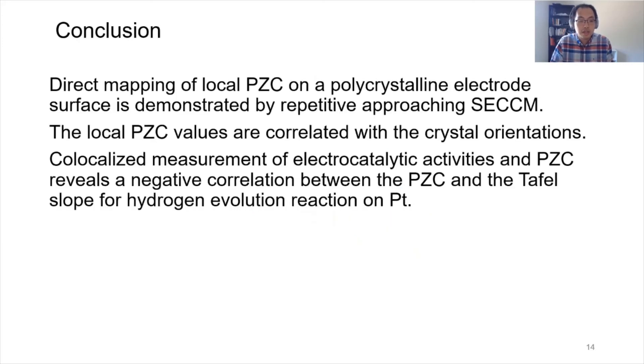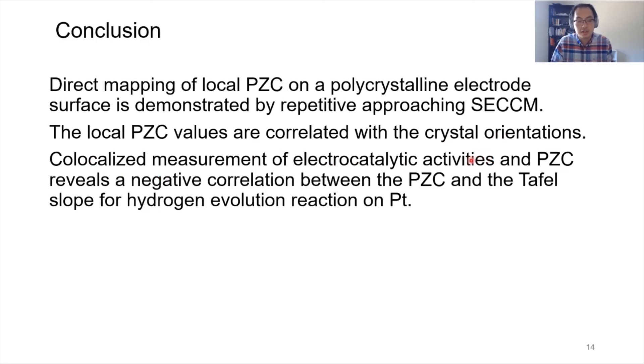In conclusion, we demonstrate the direct mapping of the local PZC using the repetitive approaching method with SECCM. The local PZC correlates well with local crystal orientations, and the co-localized measurements of electrocatalytic activities reveal a negative correlation between the PZC and the Tafel slope for the hydrogen evolution reaction on platinum.